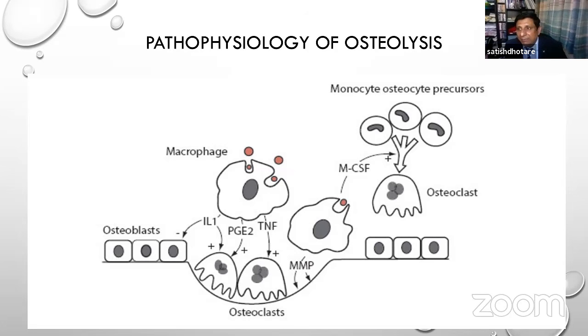What happens then? Once the macrophages get activated by engulfing these particles, they release cytokines, and these cytokines go and activate the osteoclasts, and these osteoclasts then start resorbing the bone, and that's how the osteolysis starts. That is reflected on the radiograph or X-rays in the lytic zones or lysis around the stem or the socket. And this is an ongoing chronic process. It's not an acute process which you'll see immediately within a day or within a week.